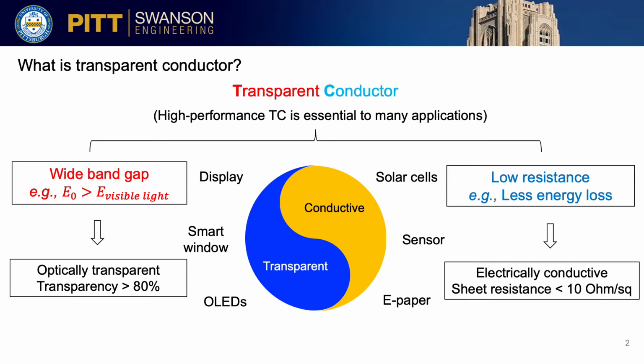However, take thin film as an example. The thinner the film is, the higher the transparency, but less conductive. As a result, the key to reach a high-performance transparent conductor is to balance the resistance and transparency trade-off.